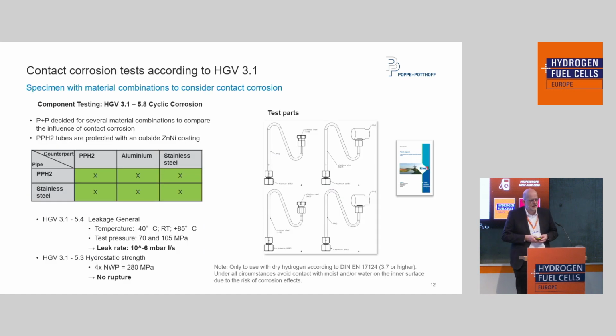We did this test with different material combinations. So you see on the right side the test parts figures, how they look like. And we have made the mix of parts of stainless steel, of PPH2, a carbon steel, and of aluminum. And in all of these combinations, we had functional-wise very good results. The function was given, even at the end leakage test with good leakage results.